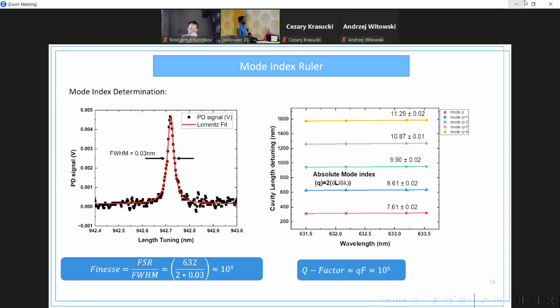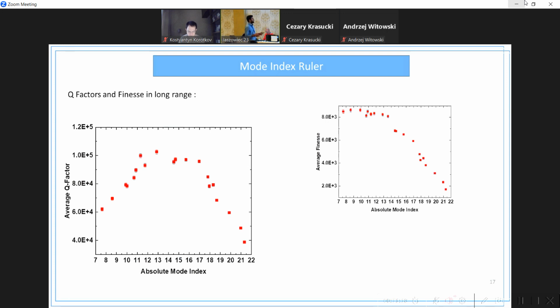Now, if you do this experiment over a large range of cavity lengths, you see that the quality factor basically starts increasing, and after some time it saturates and drops down. So this is typically a known phenomena.